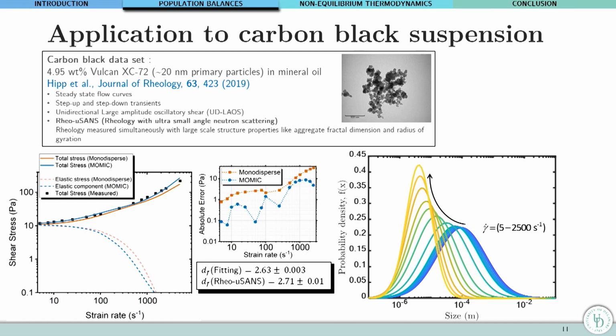We had to fit rheology to obtain the best value for the dimension of the fractals. And that fitting value came very close to the independently evaluated value through small angle neutron scattering. And this is the detail of the analysis that allows us now not only to see a change in the mean size of the aggregates with increasing shear rate from 5 to 2500 reciprocal seconds, but also a change in the width of the distribution.